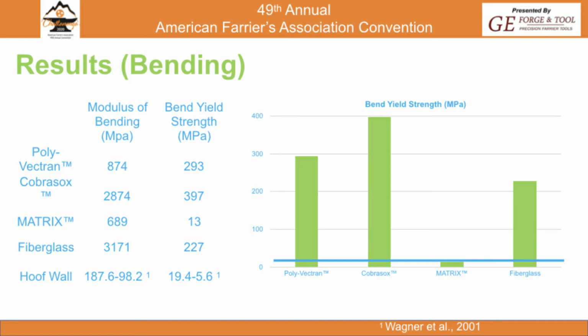It's easy to bend it. So, you know, in reality, when you look at the numbers, pretty much all of these repair materials other than Matrix all had a bend yield strength greater than that of hoof wall. And when we think about this one, this is one of the ones that I think this result leads to a lot more questions than answers, for me at least. So when you look at these, how much more do you want to increase it than hoof wall? Or can you repair a hoof wall so much that you limit independent heel movement or heel expansion of the hoof capsule? Can you actually constrict the horse's hoof capsule with a repair material?